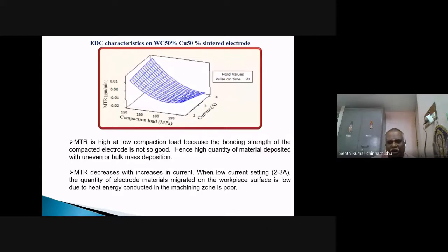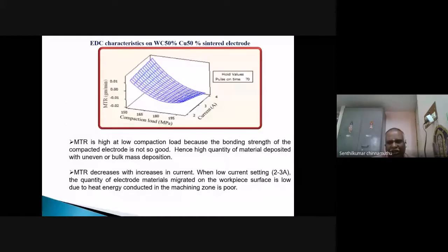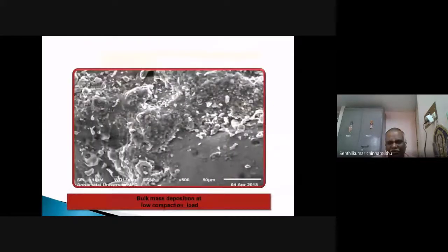See, when low current setting of 2 to 3 amps, the quantity of electrode material migrated onto the workpiece surface is low, because the heat energy conducted in the machining zone is poor, so that more amount of material is disintegrated from the tool material and deposited on the surface. If higher current is used, removal takes place instead of deposition. See, the bulk mass deposition at low compaction load, we have already seen in the semi-sintered one.